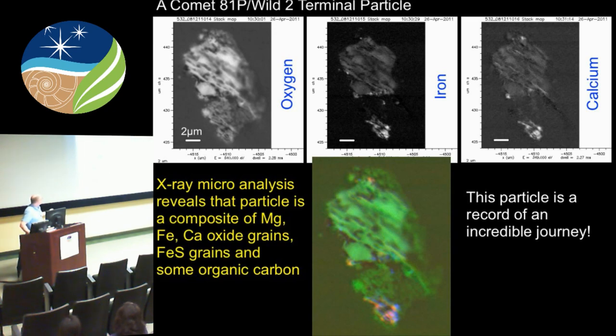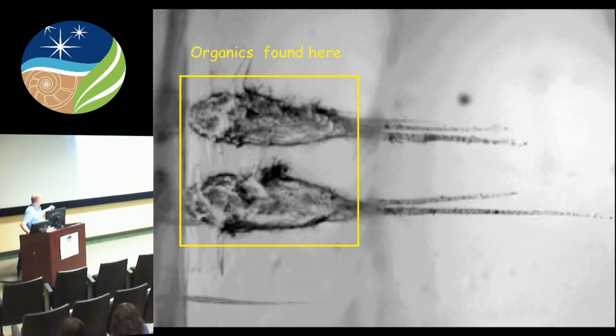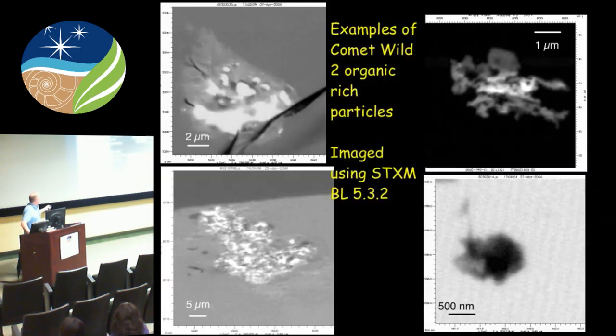So the organics, it turns out, were largely formed in these regions, or these are at least where people sectioned these regions and gave us the sections. This is where we found organics. And they were a really strange group of particles, and we still don't really understand what's going on. This one is particularly peculiar because it looks like it's highly porous. It's embedded in epoxy. This is a strange looking little wiggly thing, but it actually has a silicate grain in the core of it, very organic rich.